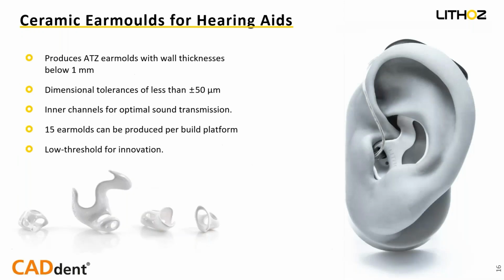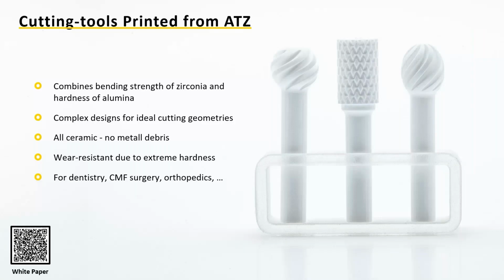An example for ATZ would be the ceramic ear molds for hearing aids. Here you can see a part that is under 1 millimeter in wall thickness overall, but the dimensional tolerances are less than 50 micrometers, which for a free form is very impressive. The inner channels are optimal for sound transmission, and you can produce 15 ear molds per building platform on an S65. Another example would be the cutting tools printed from ATZ.